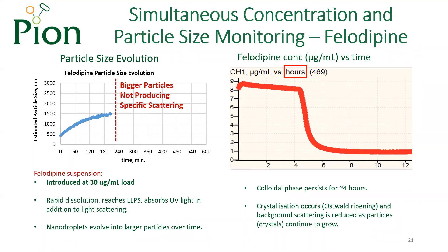In the second experiment, a solution of felodipine was injected at a drug loading of 30 micrograms per milliliter, which leads to the formation of larger nano droplets and colloidal species which are unstable over time. We can follow the evolution of the particle sizes, which starts from about 400 nanometers and reaches 1500 nanometers after about three and a half hours. Beyond this time the suspended particles are too large to produce any specific light scattering effects. Soon after, felodipine starts crystallizing, and even after injecting a drug loading of 30 micrograms per milliliter, the free concentration only reached the amorphous solubility of 8 micrograms per milliliter, before crystallizing down to the crystalline solubility value of 1 microgram per milliliter. Larger droplets or suspended crystalline material will not contribute to any specific light scattering effects that aren't entirely eliminated by the second derivative spectral calculations.